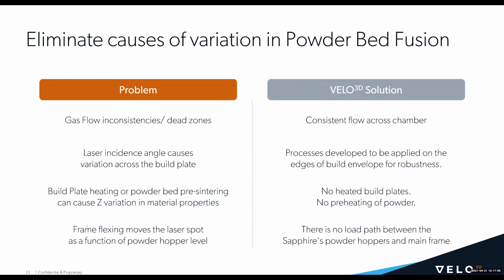Another common problem is, if you're working with heavier alloys such as Inconel 718, you can have frame flexing as a function of the powder hopper level. When the machine is full of powder, the frame flexes down and the laser spot can move. Then if you refill the powder hopper, it moves again. This makes it very challenging to characterize. However, if we look at the Velo3D Sapphire, there's no load path between the powder hoppers and the main frame, so it's not a stressed member. Because of that, we don't encounter this problem either.